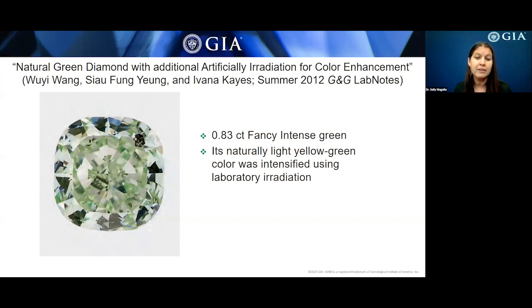Our internal records revealed that this stone had been previously at GIA and had been color graded as light yellow green. So gemological and spectroscopic features at that time confirmed that the light yellow green diamond was a natural color, and that green color was due to natural irradiation. In the resubmitted fancy intense green diamond, however, the absorption intensity of the GR1 had nearly doubled.